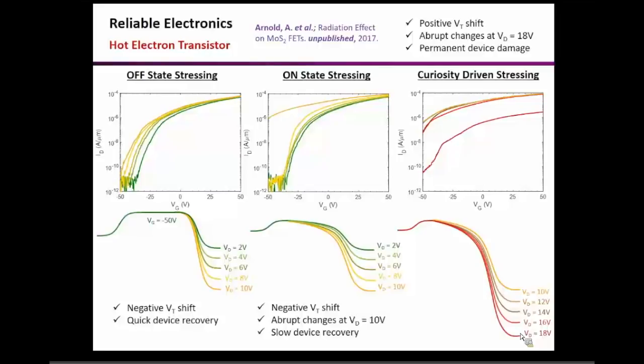Okay, so this means that in this case now we are injecting electrons, because if you have a negative shift, as I will tell you, this is hole injection into the oxide, while in this case it's electron injection into the oxide. And this is how the device starts to degrade, and you can see the electron injection is much more detrimental because now the on current dropped quite significantly, and it also introduces a certain amount of interface trap states, which was not happening with the other stressing mechanism.